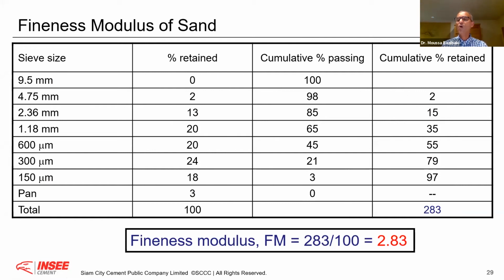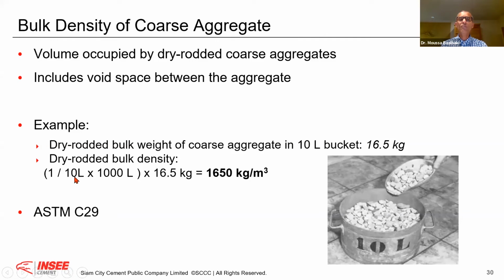Based on this one, I will know how much coarse aggregate I can put. The second important element is what I call the dry rodded bulk density of the coarse aggregate. If I have a coarse aggregate with different shape, flakiness, elongation, or a better form, or a different grading, and I take a container, a bucket of 10 liters, fill this bucket and compact it in 3 layers, and I weigh it, the better my grading, the more favorable my aggregate shape, the higher will be my dry rodded bulk density.